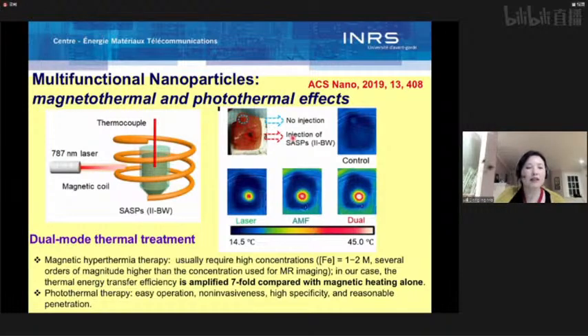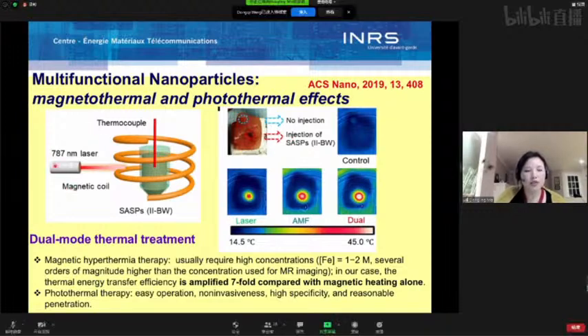I will talk about another functionality, the thermal effect. So here shows the setup. We use a 787 nanometer near-infrared laser, and we also use a coil to generate a magnetic field. And then we can put our SASPs sample, the multifunctional nanoparticle sample, into the coil. We can give the laser, or we can give a magnetic field, or we can apply both. So we put a pork tissue inside the coil. We inject multifunctional nanoparticles about 2 millimeter under the skin.